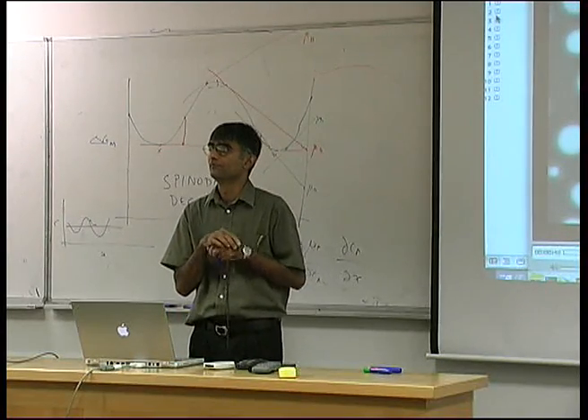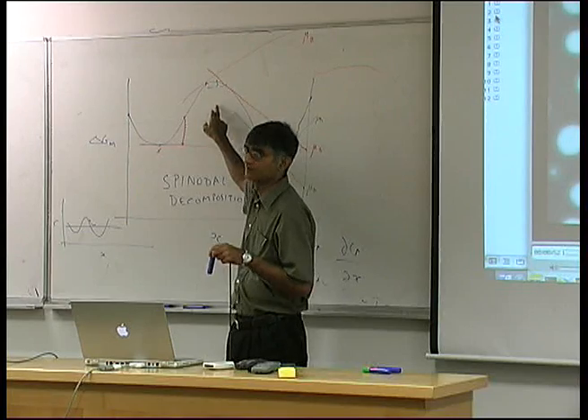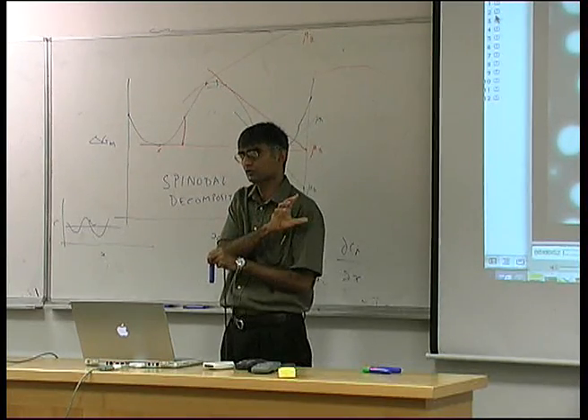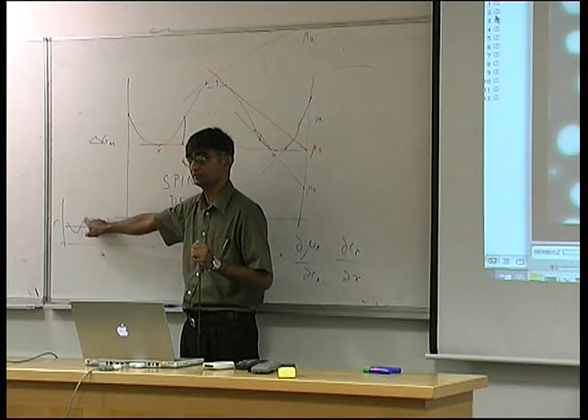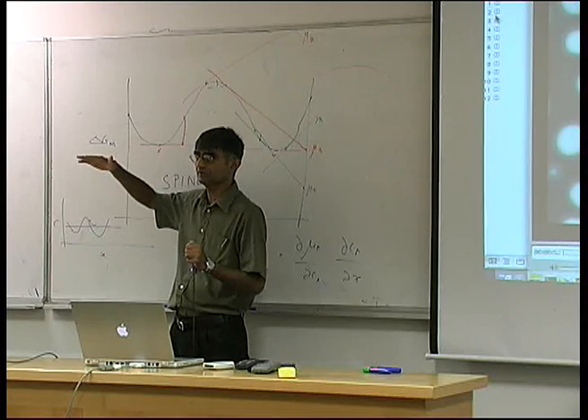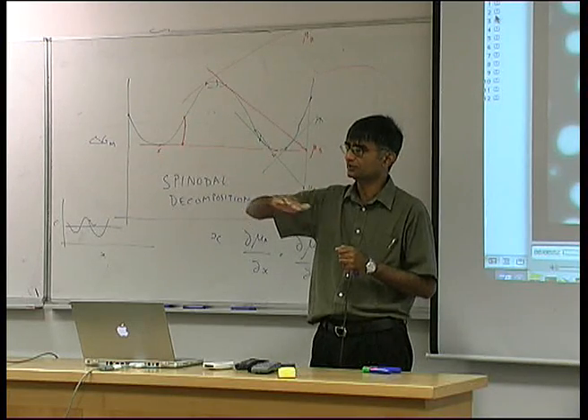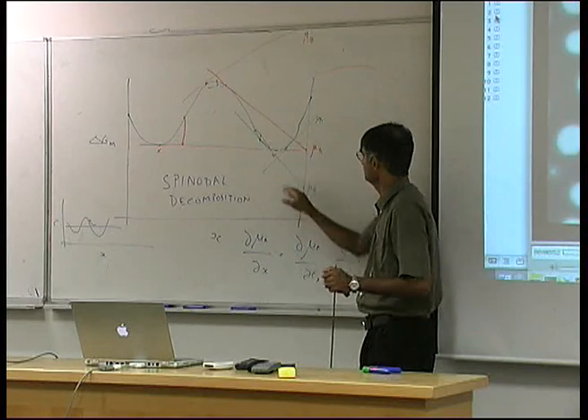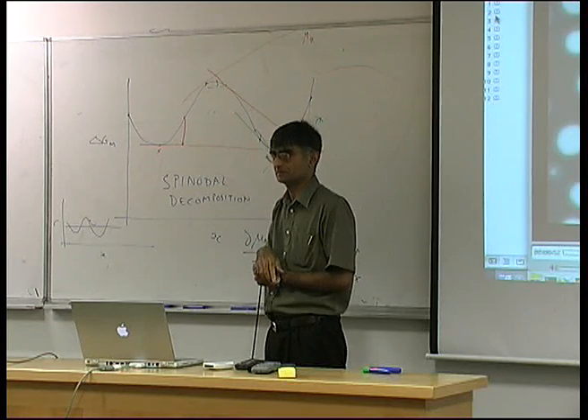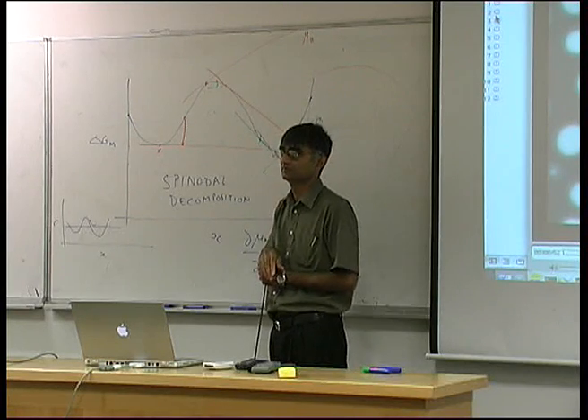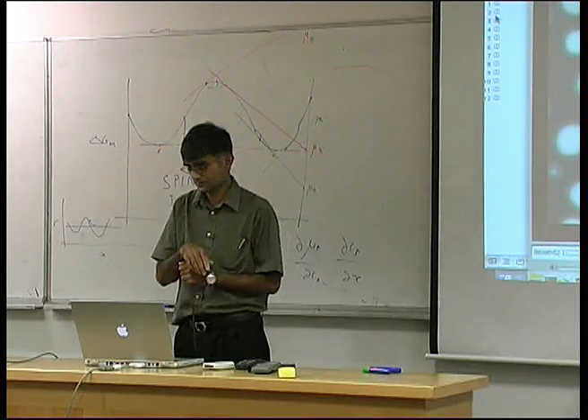Student question: At the inflection point, is the diffusion coefficient zero? Yes, exactly - so nothing can happen at that point, so you wouldn't be able to have any form of decomposition unless you nucleate. That's correct, because nothing is moving. The spinodal is defined as the region between the inflection points where decomposition starts with an infinitesimally small perturbation that grows with time - that is the identifying characteristic of a spinodal.